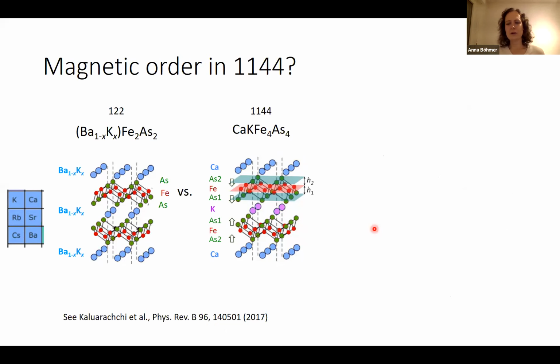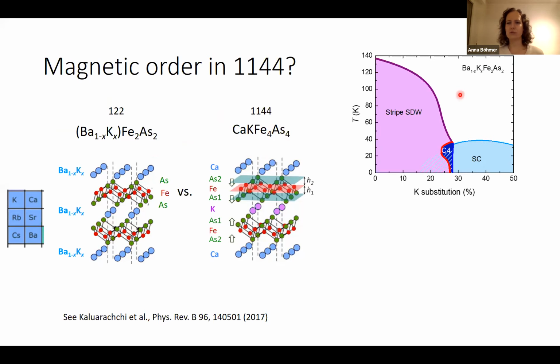But what we are wondering is, can we get magnetic order in 1144? And there have been some hints. They were from Rozier's calculations, actually, when she tried to reproduce pressure data taken and published here, that she did need magnetic fluctuations to get the correct structures. So if we want to know how to get magnetic order out of these magnetic fluctuations, we went back to this analogy. And I show you here a phase diagram of the whole of 1-2-2.